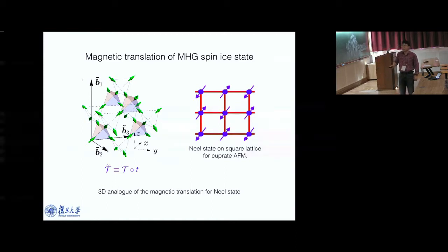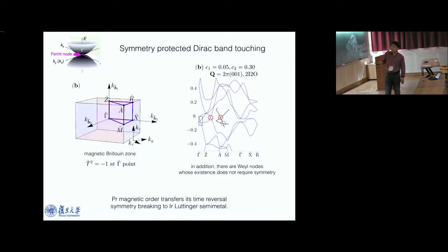So this is the antiferromagnetic transformation. This is analogous to the magnetic translation for the Néel state in a cuprate antiferromagnet. If you translate this spin to here and do a spin flip, the system stays invariant. Okay? So this is a three-dimensional non-collinear magnetic order. It's hard to visualize this symmetry, but this symmetry is there. This symmetry involves anti-unitary time reversal symmetry and translation. Because it's an anti-unitary symmetry, the original Kramers theorem has been modified because of the involvement of this lattice part.